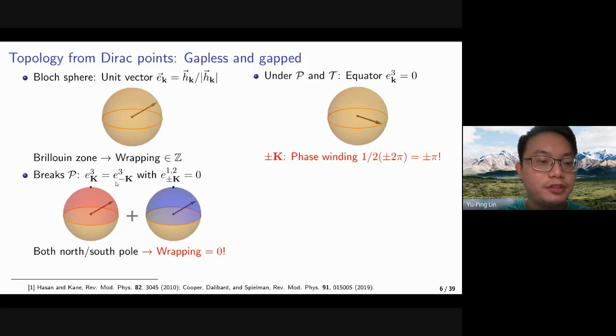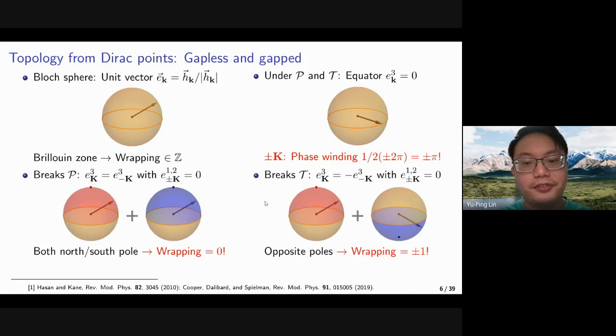If we have time reversal but no inversion, both of the poles will lie on the north pole. And it means that if we go around the Brillouin zone, we will not have a finite wrapping. The wrapping onto the Bloch sphere will be 0. However, if we break the time reversal symmetry, the third components at K and minus K are related by a minus sign. It means that K and minus K locate at opposite poles on the Bloch sphere. And if we go around the whole Brillouin zone, we're wrapping the Bloch sphere with a wrapping number plus or minus 1.